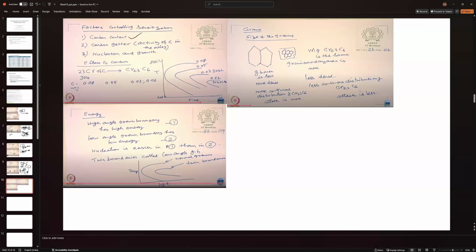So your carbon content affects it. And grain boundary is affected. If you have high energy grain boundary, it will have more nucleation, easier nucleation. Okay. So this low angle grain boundary is also called twin boundary. The twin boundary will take longer to sensitize the steel for IGC. And yeah, carbon getter or your stabilizing elements, they also affect your sensitization. Okay.